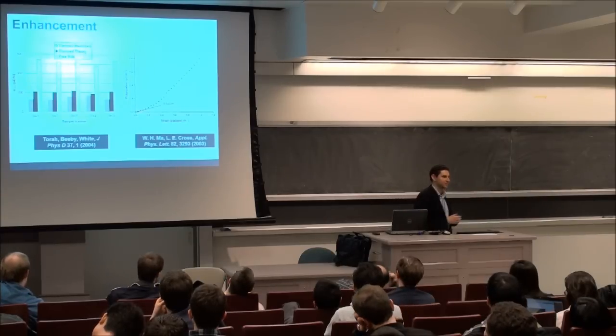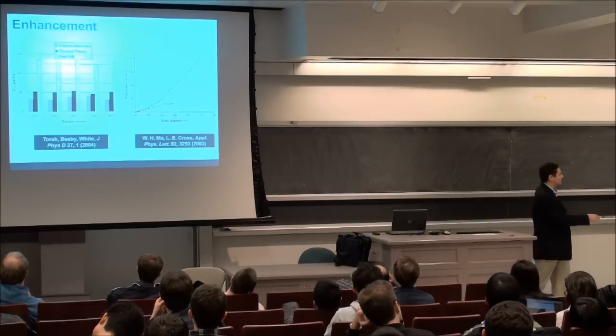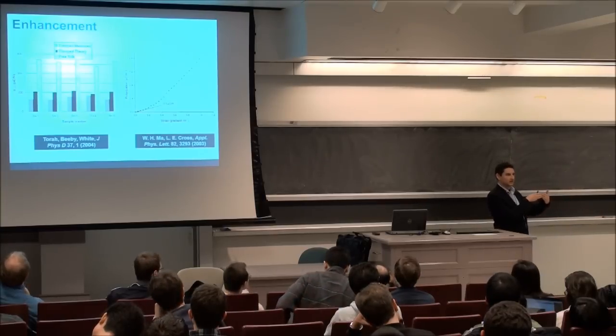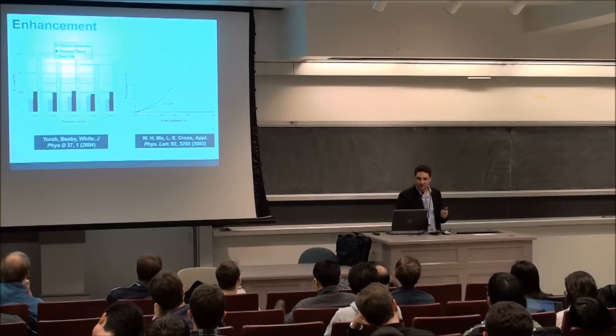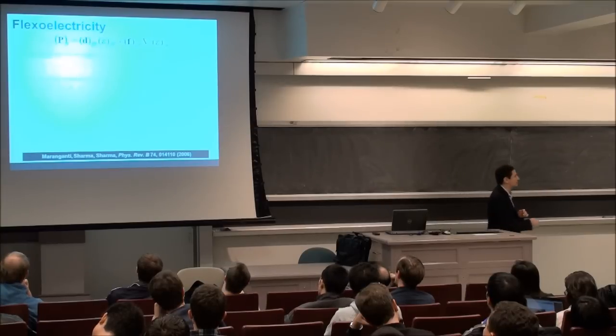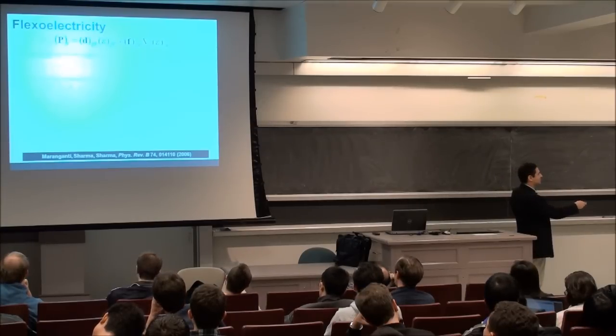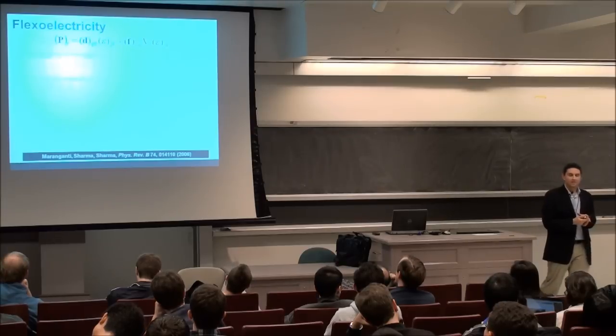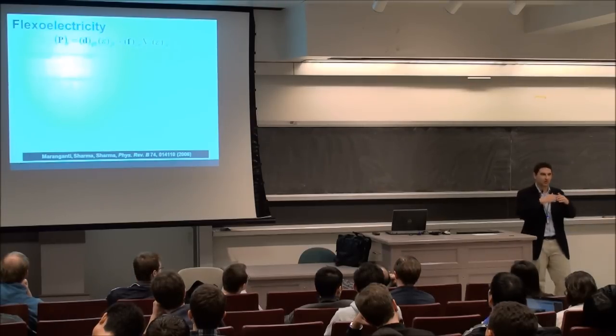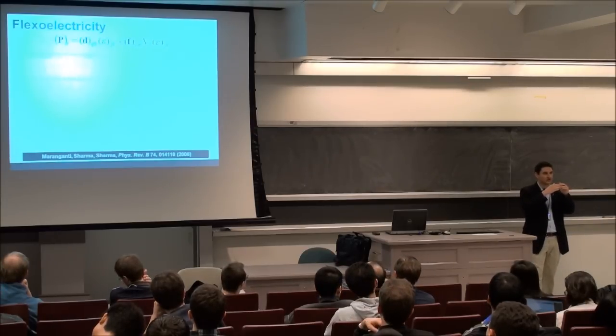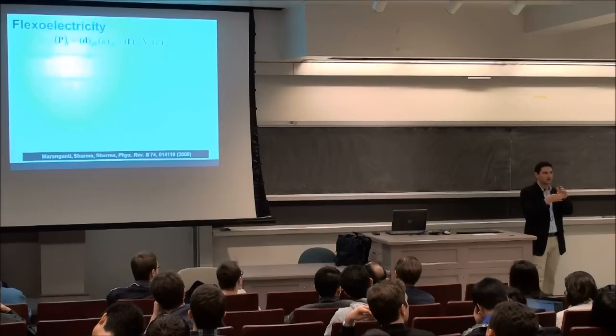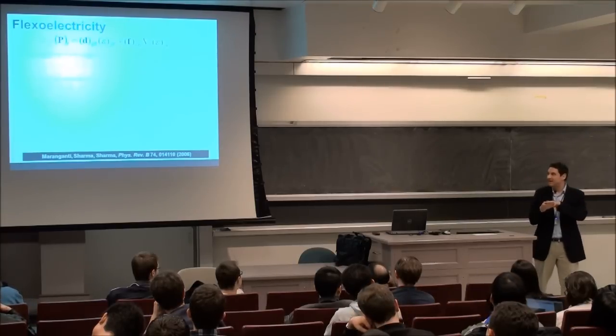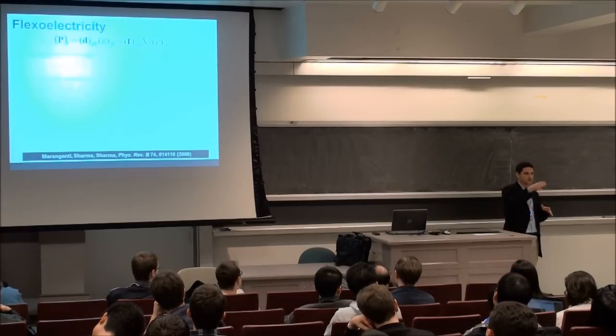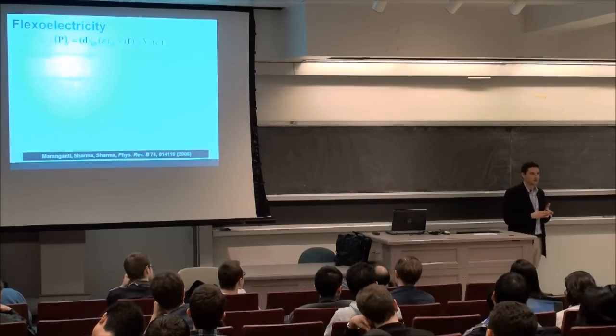This was work that was pioneered by Eric Cross at Penn State. You can create a polarization just by bending a material. So if you look at the equations here, the first part is our D constant that we talked about before, which is proportional to strain. But this flexoelectric contribution is proportional to this strain gradient, going from expansion to compression in this buckle part. And in our case, our strain gradients are enormous because these are nanoscale buckles here.